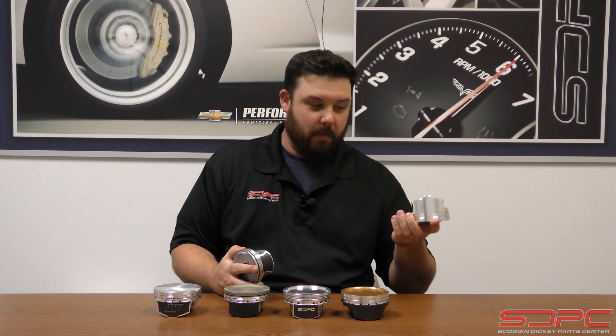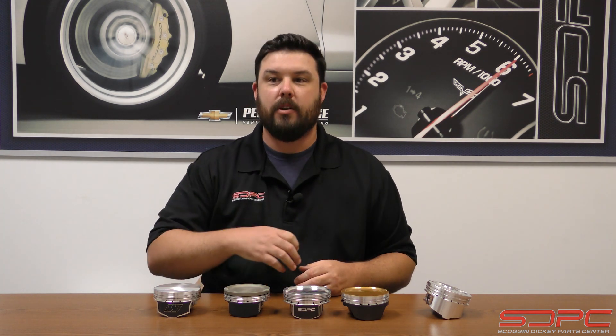As you can see, there are different ones here. They even make different alloy types. There's the 2618 forging, which is actually the most common — that's the strongest, and the one most people get on an off-the-shelf piston. But they also make a more street-friendly 4032. I think Mahle makes one that's a really good balance between the hyper eutectic and a full-blown 2618 forged piston. You kind of need that sometimes — something that can fire up every day, drive around, sit at the Whataburger drive-through with the AC going, and at the same time make 800-plus horsepower under boost. A 4032 forging is not as strong as a 2618, but it's definitely a lot stronger than what the OEM can offer.